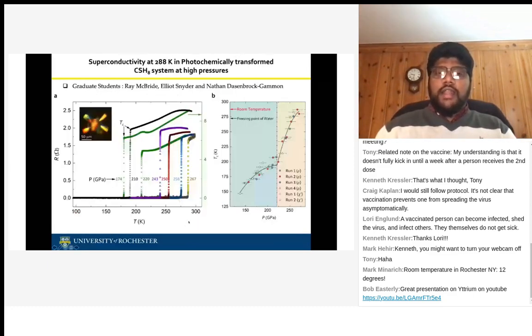in electrical resistance at 288 Kelvin, which is 15 degrees Celsius and roughly close to 58 degrees Fahrenheit. So it's a chilly room, but still, it's considered a room temperature superconductor. So in this graph, what you're seeing is pressure versus transition temperature. The further you go up in pressure, it goes up and up and saturates, and then suddenly goes up all the way to room temperature.